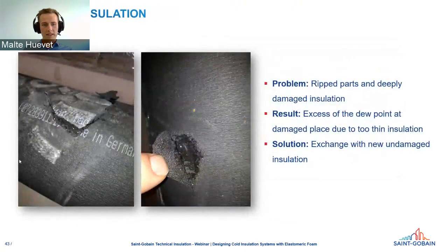So this is a good example of how it will look after an insulation gets damaged. Of course, the insulation itself is completely dry, but especially at the point where it was punctured or the piece was ripped off, the insulation isn't thick enough to stay above the dew point, and then we will see a situation like that: in the damaged part, condensation water will occur, and that's of course not what we want to have.